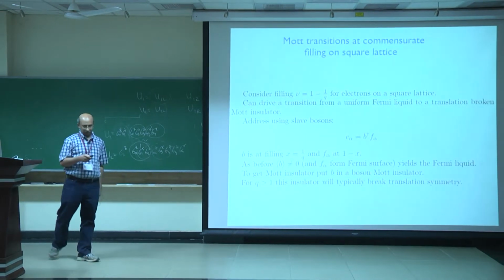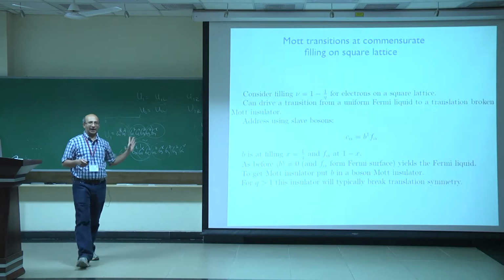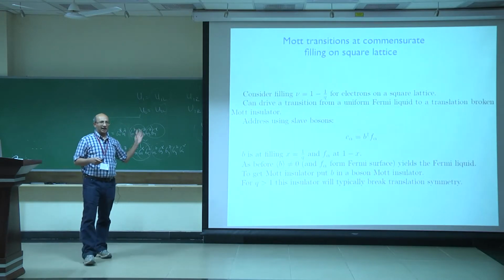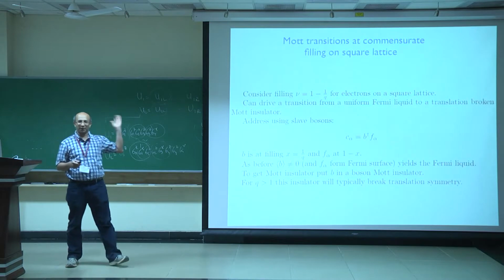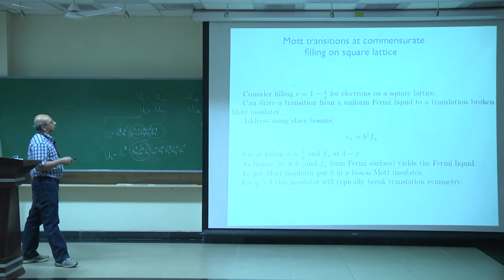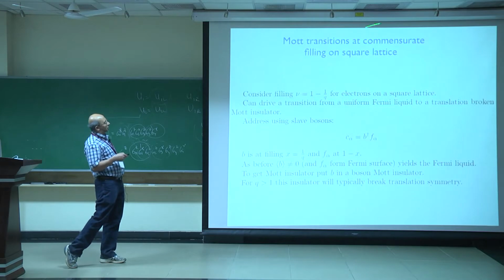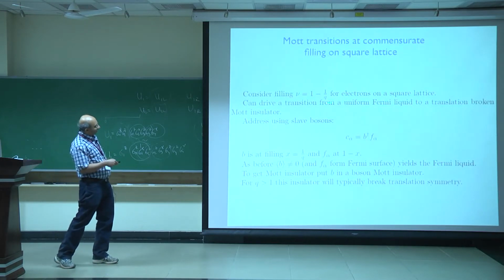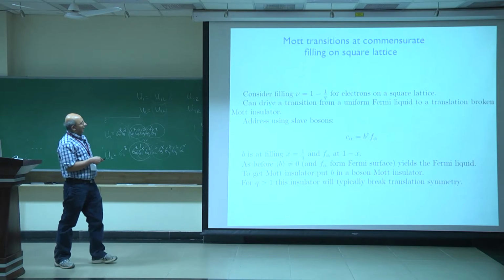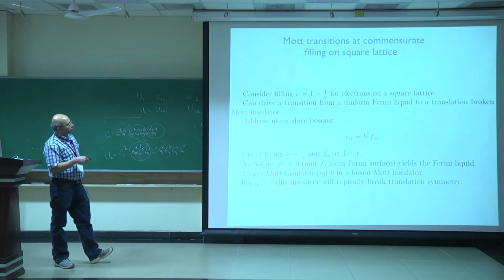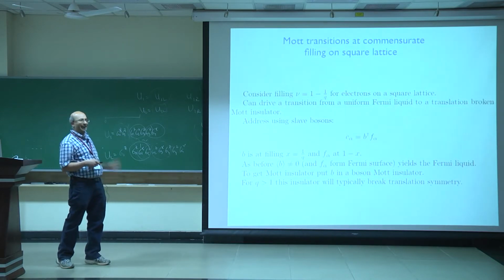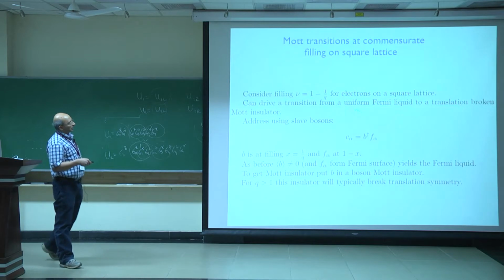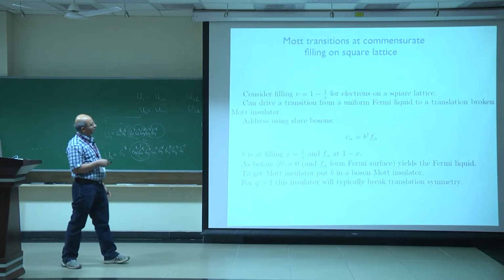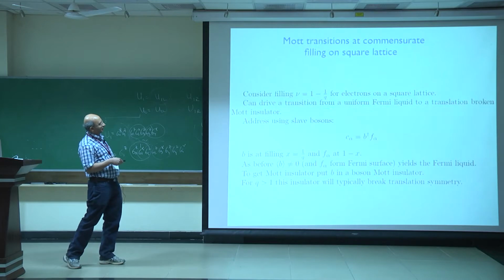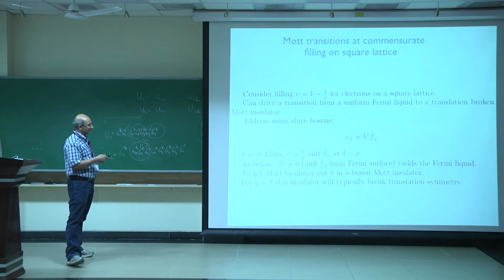Okay, so now I want to come back to the square lattice because I'm thinking about cuprates. And once I'm away from half filling, there's no nesting or anything that I need to worry about. So I want to think about the Mott transition at commensurate filling on a square lattice. I want to consider filling 1 minus 1 over q. And in principle, I can drive a transition from a uniform Fermi liquid to a translation broken Mott insulator. I necessarily need to break translation. I actually don't necessarily need to, but typically I will need to break translations to get a Mott insulator at this filling because there are not enough electrons to fill up all the lattice sites.